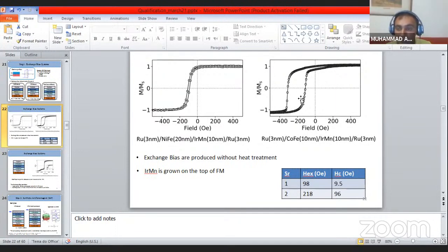Yes, this is from an application point of view. I have used this kind of exchange bias in my spin valves, if these structures were considered for use in memory elements. This is the main goal. It has a higher coercivity for the memory applications. For switching applications we use nickel iron, which has a low coercivity, so it can be used as a switching application.